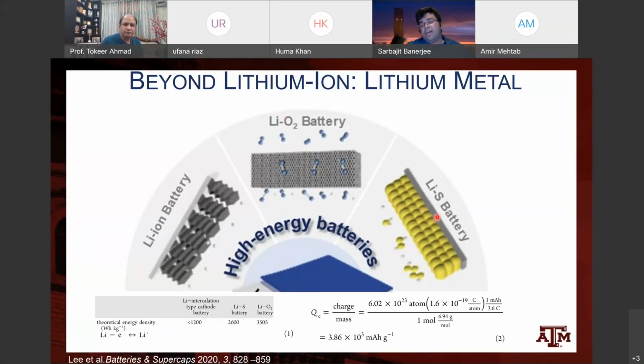And you can see why, straight up, this is such an attractive concept. Instead of cobalt oxide or manganese oxide or one of these expensive elements, if you can use sulfur, which is dirt cheap and a byproduct and so light, or if you can use oxygen on demand without even having a real cathode, these are two very attractive concepts for getting very high theoretical capacity. So again, for a lithium sulfur battery, the number is 2600 watt-hour per kilogram. For a lithium oxygen battery, the number is 3505 watt-hour per kilogram.